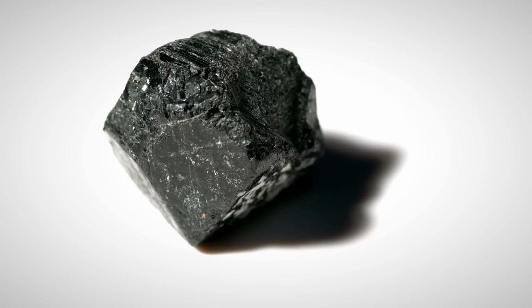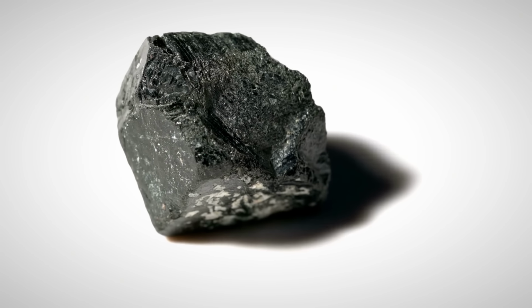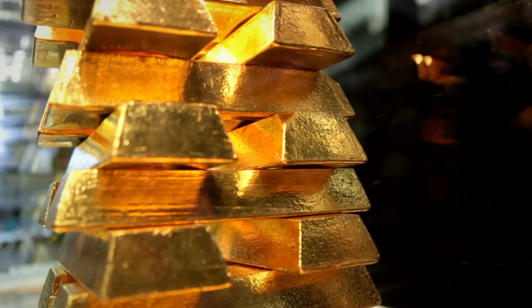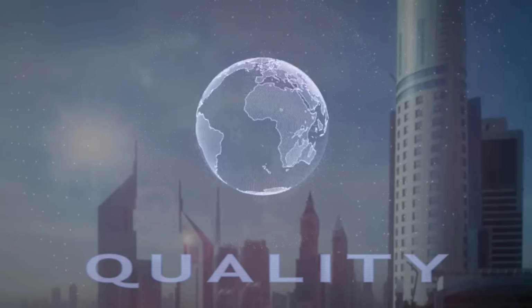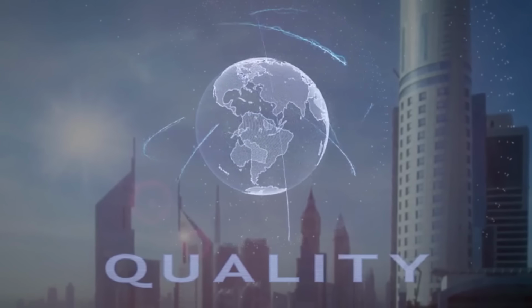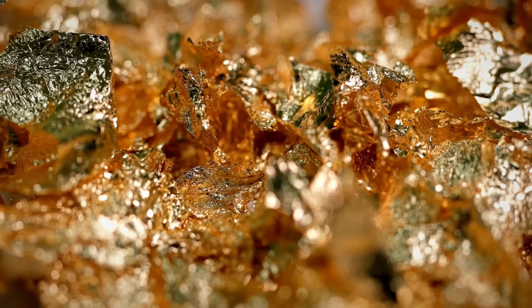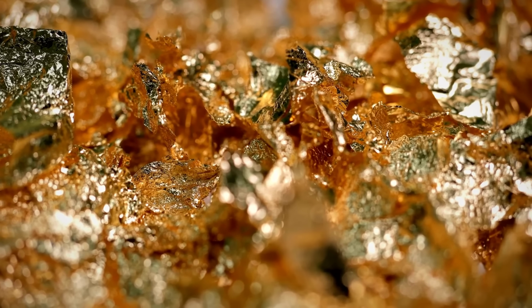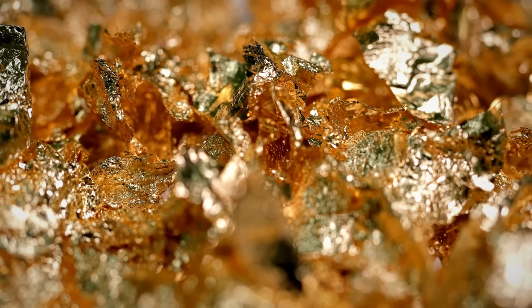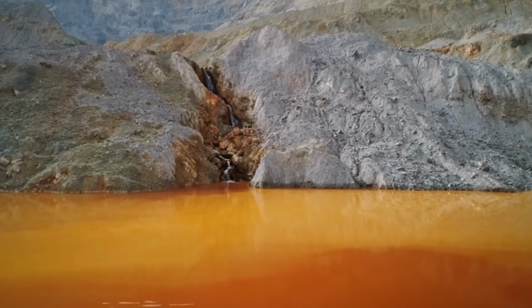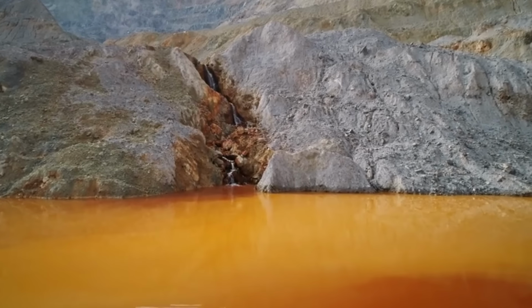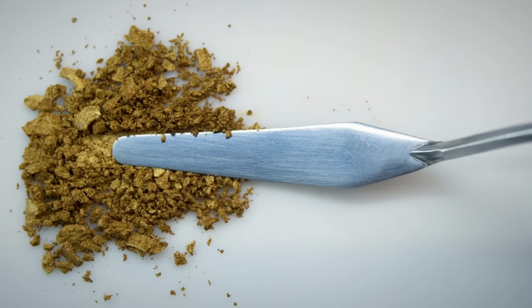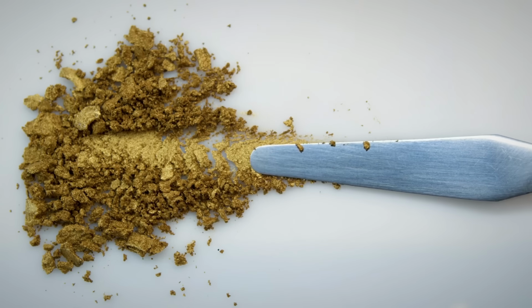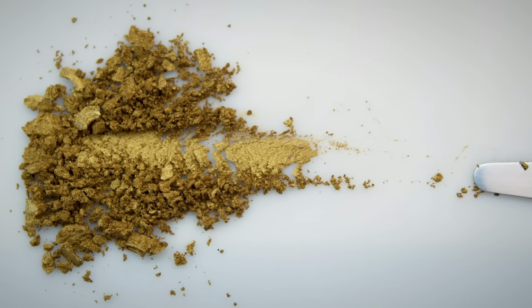Quartz, being relatively stable, contracts slowly and uniformly. But hematite and limonite, the iron oxides formed during roasting, shrink more rapidly. If gold is present, either as tiny liberated grains or residue from decomposed sulfides, it doesn't contract in sync. The result is mechanical strain along boundaries where gold meets oxide or oxide meets quartz. These zones split, tear, or flake depending on the cooling rate. A slow air cool, over 30 to 90 minutes, maximizes this effect, creating widespread cracking that exposes previously sealed gold pockets.